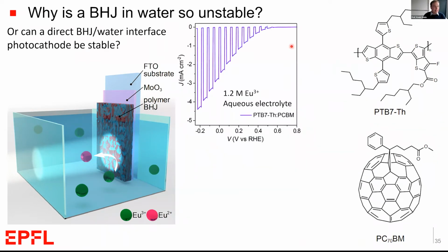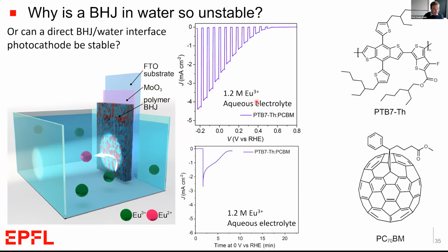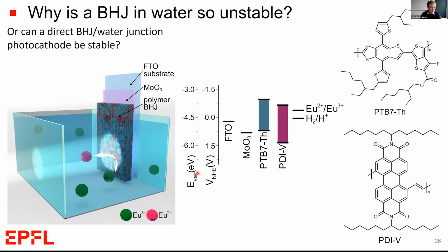So we can see that if we use a bulk heterojunction of these materials, we get pretty decent photocurrent, about 3.5 milliamps per centimeter squared in this aqueous electrolyte with europium. But we see, similar to the other work, very poor stability performance. And after only 10 minutes, the electrode is essentially dead.